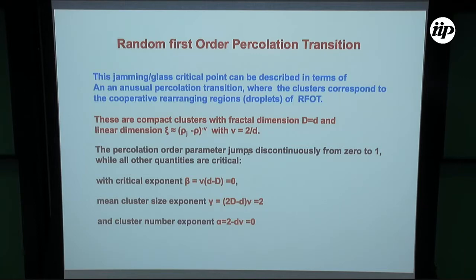These are clusters which are compact and have a fractal dimension capital D equal to d, the dimension. And the linear dimension of this cluster diverges with an exponent rho j minus rho to the minus nu, where nu is 2 over d, the exponent of the random first order transition. So the percolation order parameter jumps discontinuously, just like in a jamming transition, from 0 to 1,